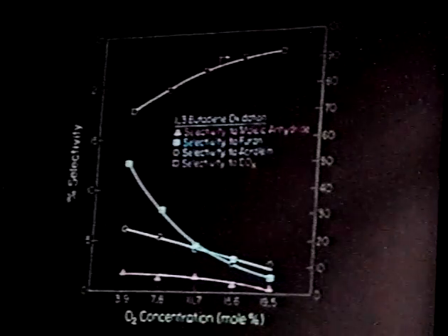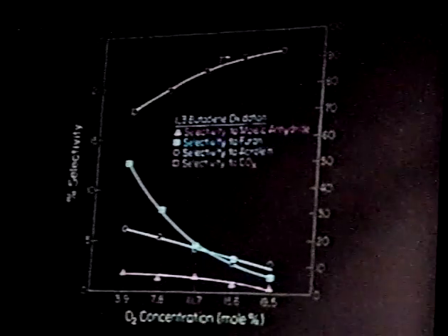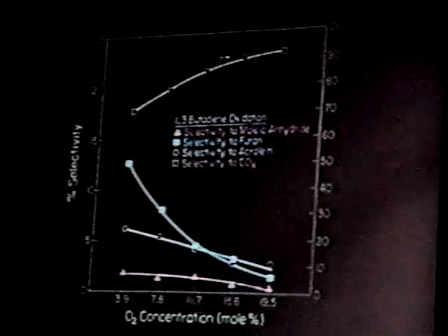One is that formation of furan over manganese molybdate does not require presence of gas-phase oxygen. It is more associated with the lattice oxygen. And it could also suggest a possible competition between butadiene and oxygen for the same catalytic site. When we use furan oxidation over manganese molybdate, the only oxidation products that we observe are complete oxidation products.